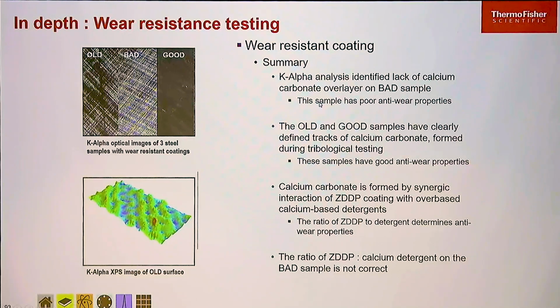The way they apply the ZDDP on there also involves a kind of calcium detergent they use to apply it to the surface. And if that isn't applied in the correct ratio, you don't get this carbonate forming, and that causes poor wear performance on the material.